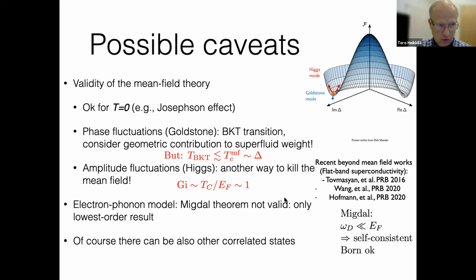So what we do here is that we kind of do this BKT transition, but we start from the mean field and we calculate the superfluid weight in the mean field. There are also some completely beyond mean field works which have studied this flat band superconductivity, but I would say that typically their results agree quite well with the mean field results that contain this BKT physics.